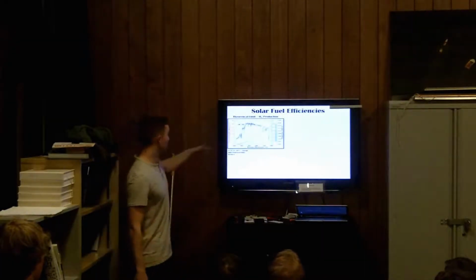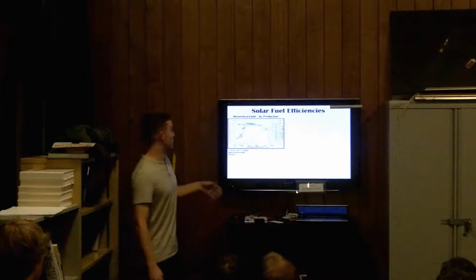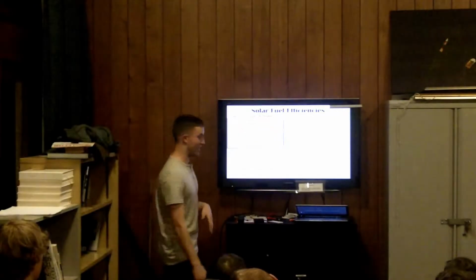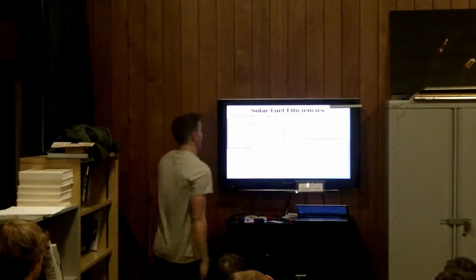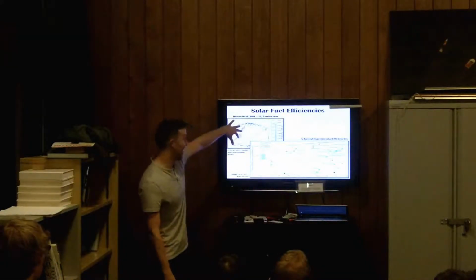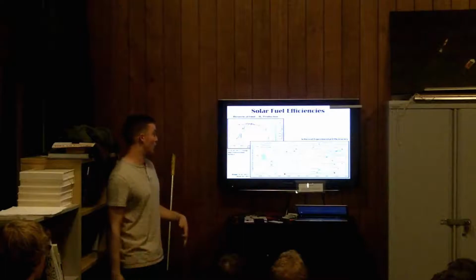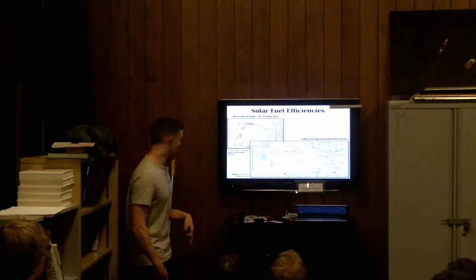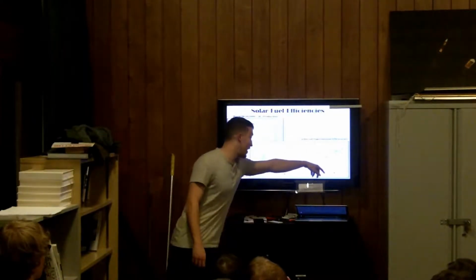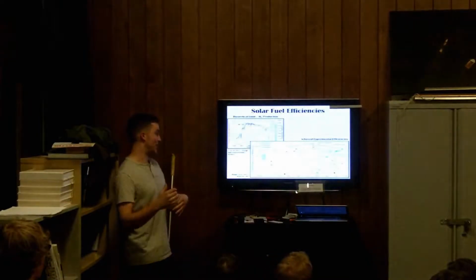So you can see that the theoretical efficiencies that we're limited at are quite reasonable, actually, up to between 30 and 35% if we had the perfect material with 100% energy conversion. But here are the actual achieved experimental efficiencies. And this is a logarithmic scale here, so you can see that most achieved figures are actually down below the 1% efficiency value. The type of materials that I work with would fall mostly on this pink or red line here. And you can see that there's still a long way to go as far as the photoelectrochemical energy conversion to solar fuels.